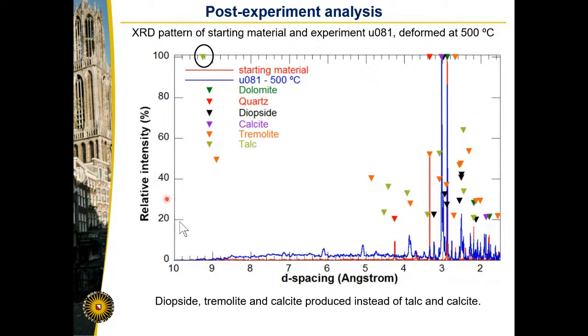Here's an XRD spectrum. In red is our starting material, which is quartz and dolomite. So the different mineral phases are shown with these upside down triangles. And if you would have talc, then we would expect a pronounced peak here, which is not present. Instead, we see peaks in the blue that are related to diopside, so those are the black triangles, as well as tremolite, which are the orange triangles. So clearly, we are producing different minerals that are causing different fault strengths. So this would suggest that the Zuccale fault would not be weak any longer at higher temperatures.